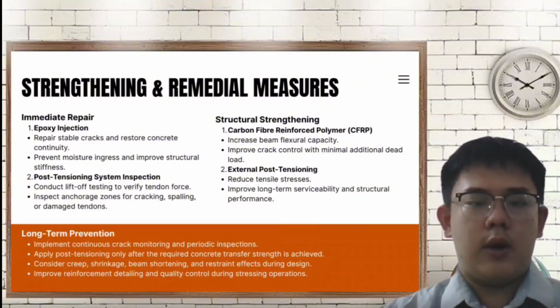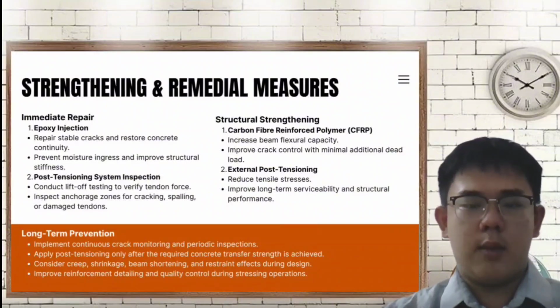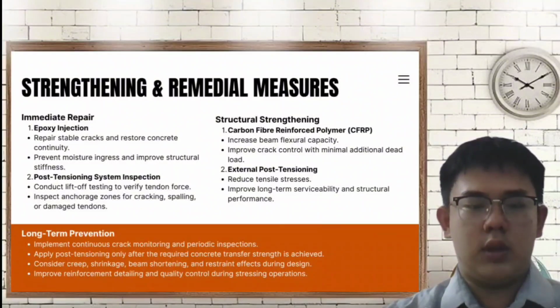I'm Tawiki. Now I will explain the strengthening and remedial measures of our project. First, for immediate repair, stable cracks can be repaired using epoxy injection. This method restores the continuity of the concrete, prevents moisture from entering the crack, and helps improve the structural stiffness. Next, a post-tensioning system inspection should be carried out. Lift-off testing is used to verify that the tendons still have the required stressing force. At the same time, the anchorage joint should be inspected for any sign of cracking, concrete spalling, or tendon damage.